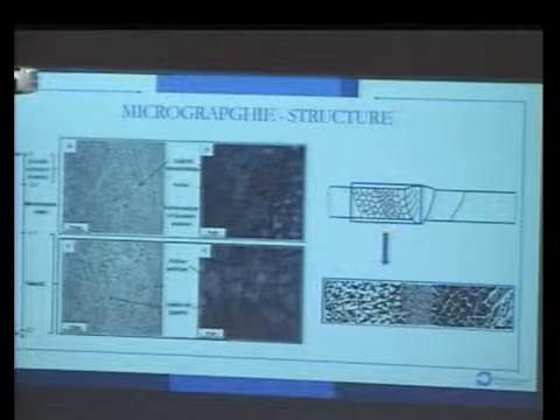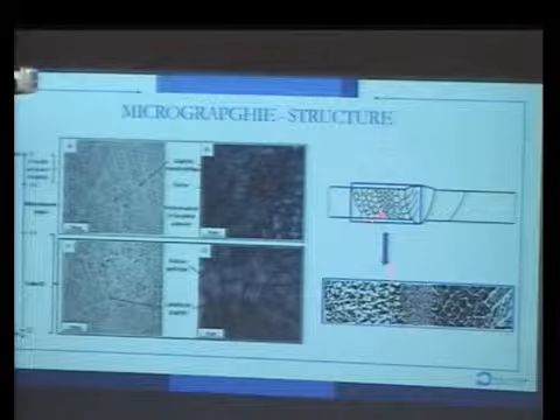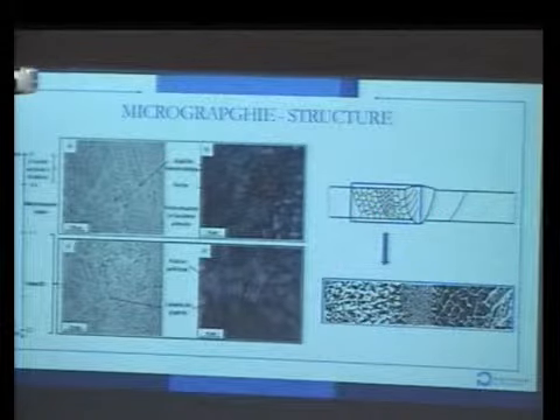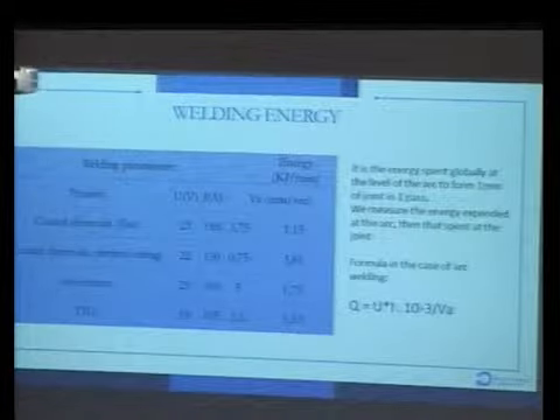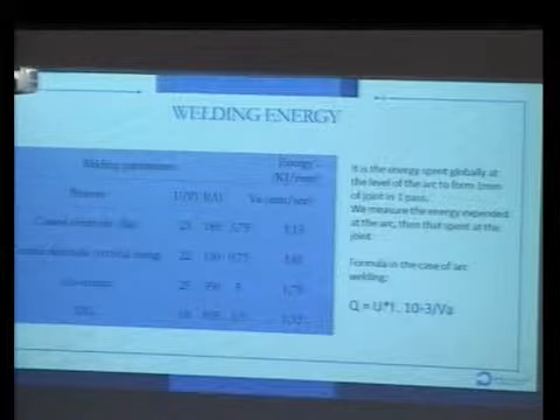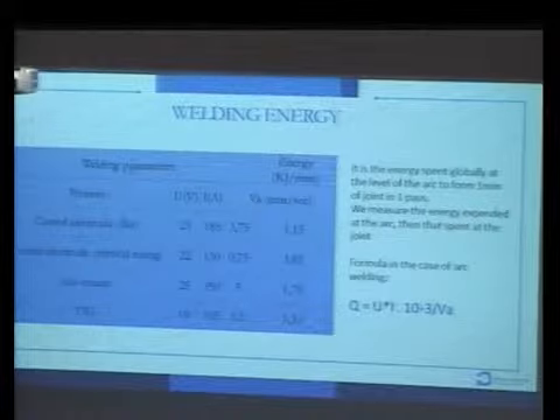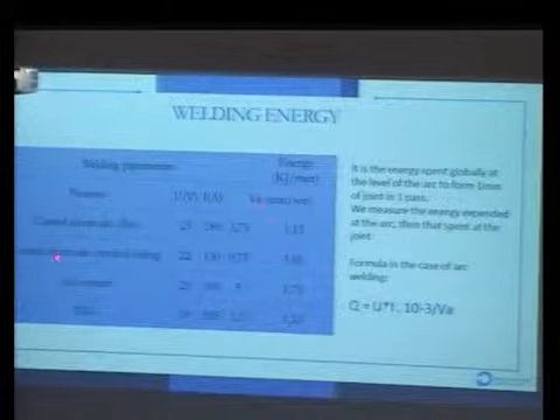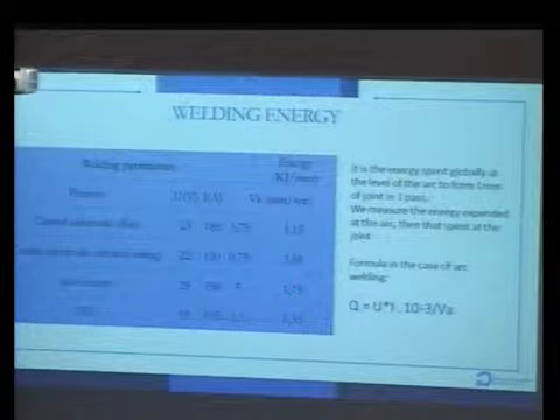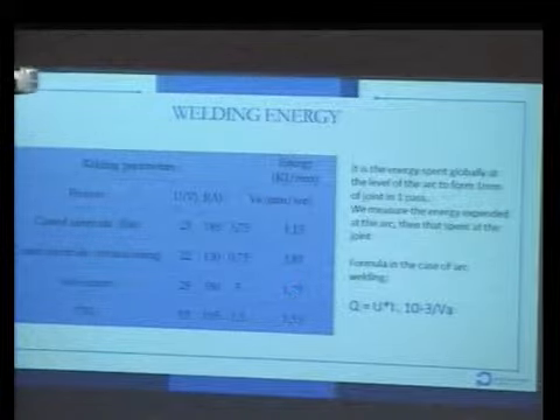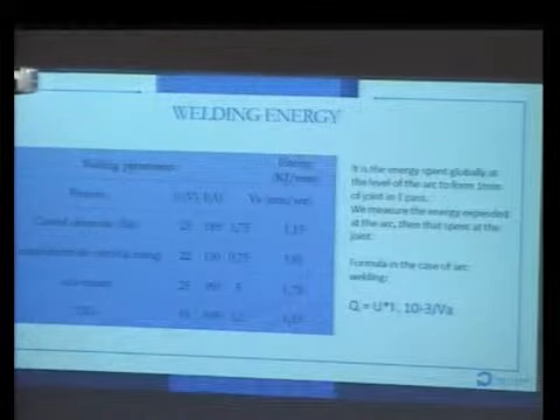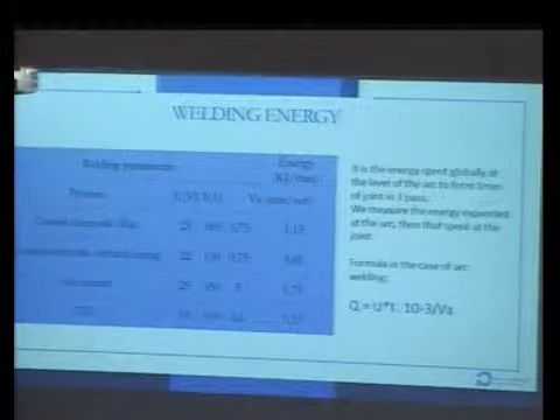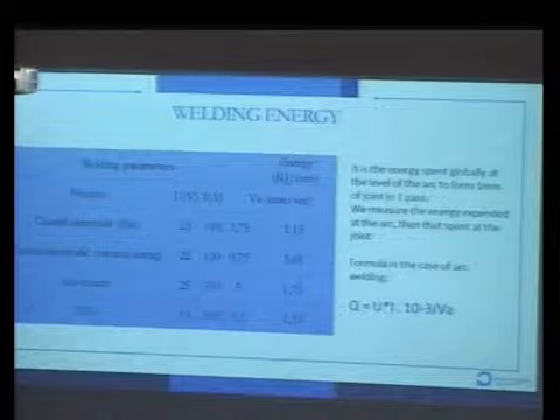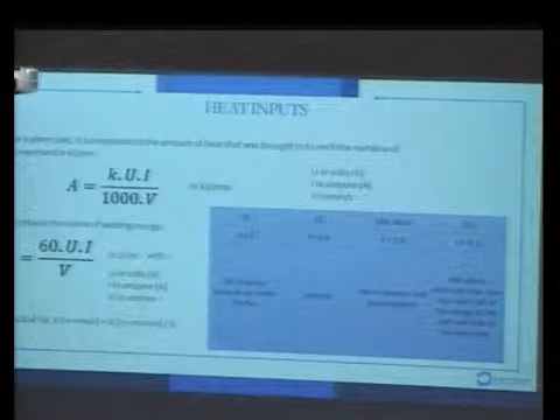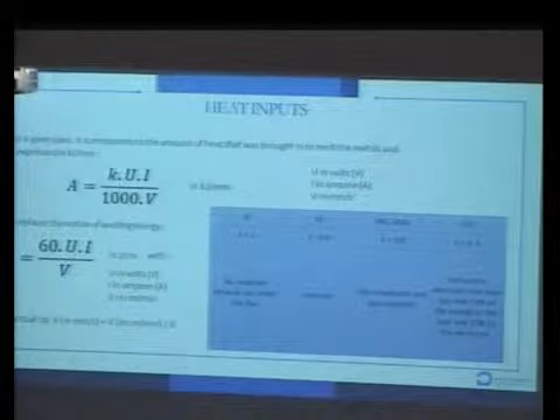So when you weld here, you have a melted zone, and at the side of the welding zone you have different structures of welding. What is important? The first very important part is the welding energy. If you put in a lot of energy, if the energy is high, for example here, the piece has high temperature inside, and the cooling will be slow. If the energy is low, it will cool very fast, and you have a risk of quench. So the heat input during welding is very important for the risk of quench.